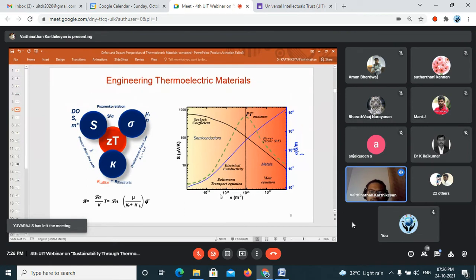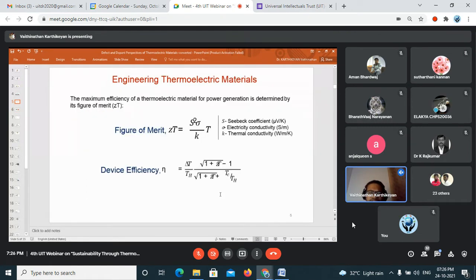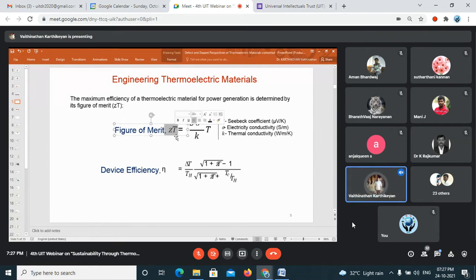So, the main problem with the traditional thermoelectric materials is that when you try to increase the Seebeck coefficient to get a higher efficiency, the electrical conductivity goes down. And when you try to improve the electrical conductivity, the Seebeck coefficient goes down. So these two are coupled together, and it's really difficult to decouple them and increase the Seebeck and electrical conductivity together. When you increase Seebeck and sigma together, the numerator value goes up, and the efficiency of the material goes up. That's what every researcher in this field is trying to achieve.